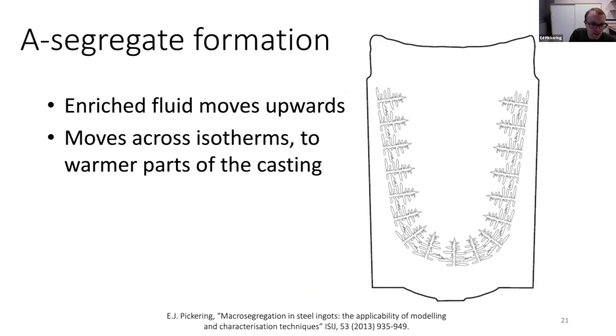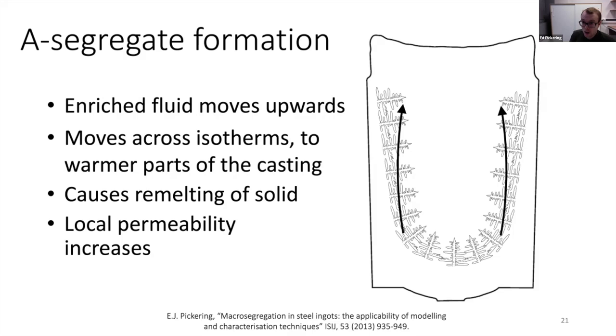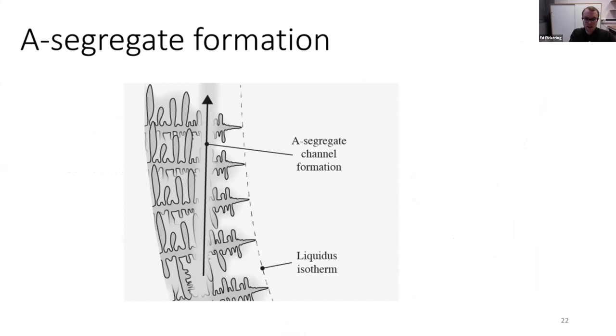it causes remelting of the solid and increases local permeability. If you imagine you've got very enriched, solute-rich fluid moving from here, let's say, to over here, crossing isotherms, in so doing, it tends to melt the solid around it and it forms these channels. So basically we have something like this where the enriched liquid moves upwards and it crosses isotherms and melts the solid. It's a bit like having a mixture of ice and water and adding salt into it, increasing the solute concentration, that tends to melt the solid. That's essentially what's going on here.